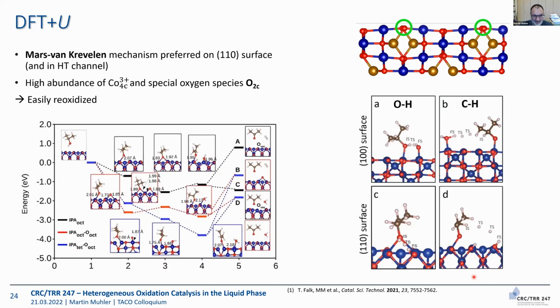And then, of course, we asked Rosica Pencheva again for calculations, now on the 110 surface. And this surface is very different. Now there is just 4-fold coordinated octahedral cobalt 3+, highly reactive, and a special oxygen species that is just 2-fold coordinated, as indicated here. And we think, supported by theory, that the presence of this oxygen species allows to have a stable catalyst because the larger particles are much faster reoxidized than the small ones. That would be here the pathway C, according to the Mars-van Krevelen mechanism, that is more favorable, according to theory, on 110 surfaces.